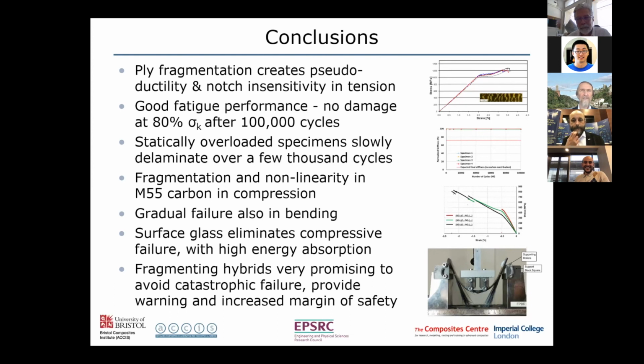In terms of the effect on impact, we've done a limited amount of work, which does suggest that we might get a little bit less delamination under impact loading, but I wouldn't really like to stress that too much because we haven't done enough yet. So what happens in terms of impact and compression after impact still needs to be looked at, but there are some indications that the behavior will be quite good, and we have already shown that we get reduced notch sensitivity in tension. We haven't actually looked at that in compression, but I would expect, because the mechanisms are quite similar, that we'd also see resistance to damage in compression as well. So I think there are indications that it will be good, but it's too early to say yet.